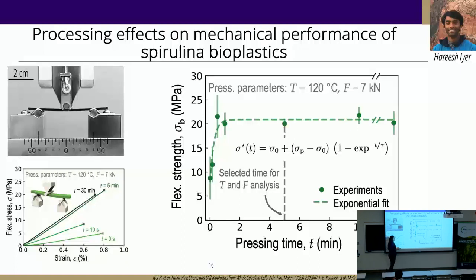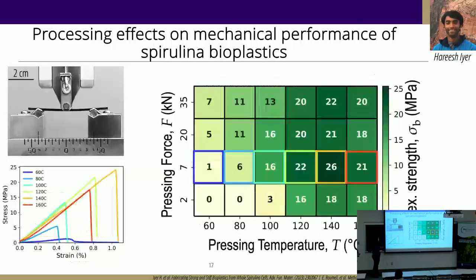We have a characteristic time, tau, that denotes to us when significant change has occurred. We don't know yet what this change looks like, but we do see that after a couple of minutes, you already have a steady state flexural strength in your results. We chose 5 minutes, which is actually longer than the characteristic tau time, because we wanted to not just reach the plateau, but we wanted also to have as small of an error bar as we could. And I hope you will be paying attention to the error bars here. They are not, I guess, as scary as I thought initially, because this is unfiltered biomass, nothing has been extracted. So we do have error bars, but I don't think they're pretty bad.